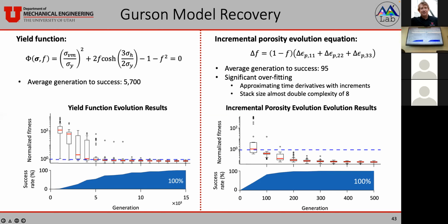95. We do see significant overfitting though. So by generation 500, the best models have a normalized fitness of 0.1. So about 10 times better than the fitness of this equation. So why might that be? There are a couple of reasons for this. First off, you're approximating the time derivatives with increments. Remembering back, the actual porosity evolution equation had derivatives. Also, the stack size of 15, which I took from the yield function results, that's almost double the complexity of the porosity evolution equation. And as we've seen, more complex equations are more prone to overfit.